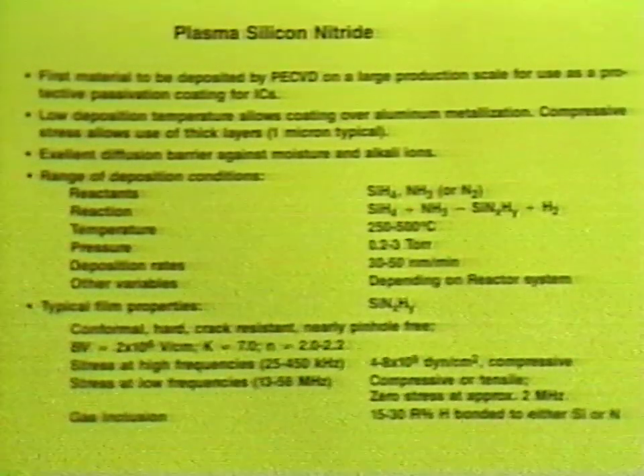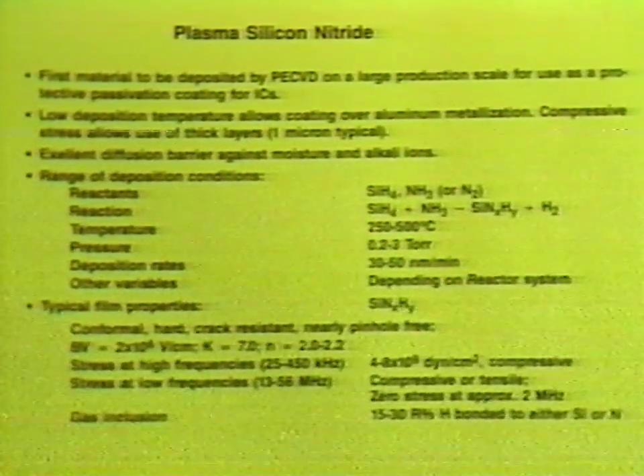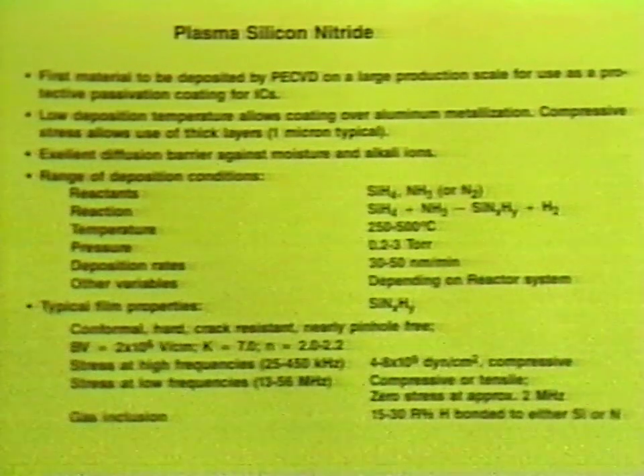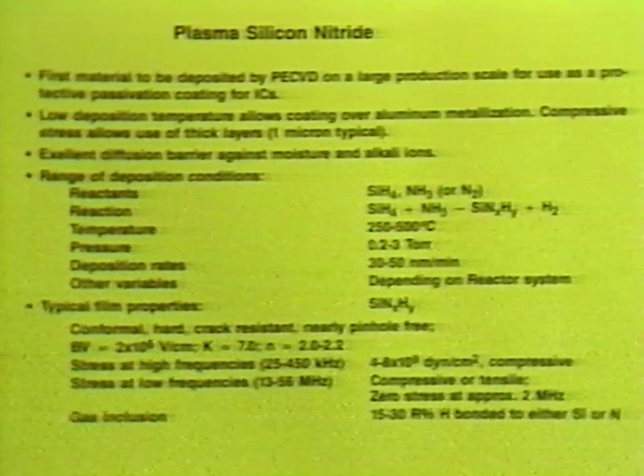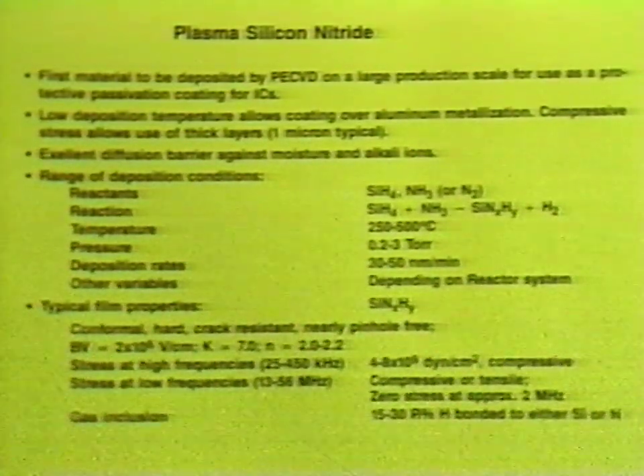because that will cause problems later on in its application. If we have a frequency in the range of 13 to 56 megahertz, then the stress can be compressive or tensile, and we observe it as essentially zero stress at approximately 2 megahertz. So as you can see, the properties of the film, especially stress, is dependent on certain parameters. Frequency is only one, but there are other ones that are determining the type of stress one will obtain. Gas inclusion here, of course, is mainly the hydrogen, which may be from 15 to 30% bonded to either silicon or nitrogen. And of course, that will produce a problem of outgassing later on, which may produce blistering of the film and effects on device performance. So that hydrogen is a very undesirable situation in the case of the plasma nitrides.